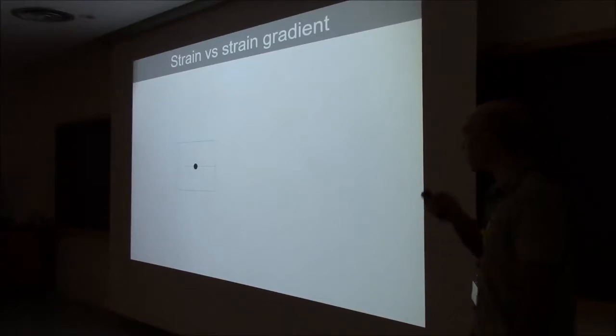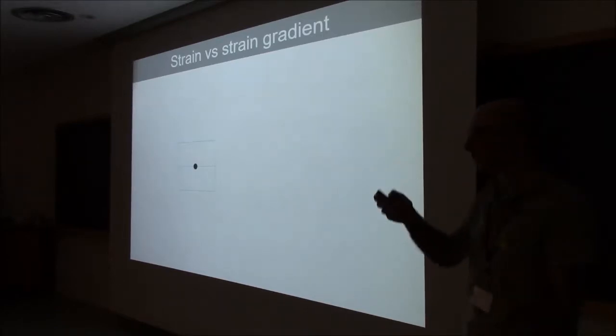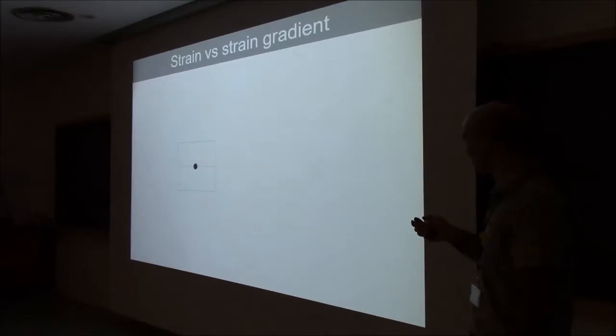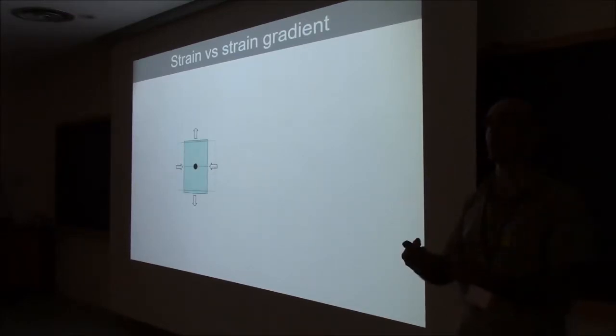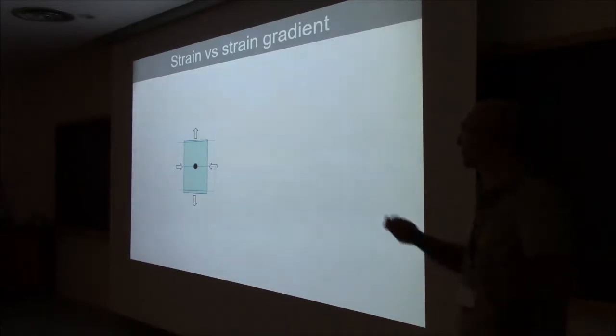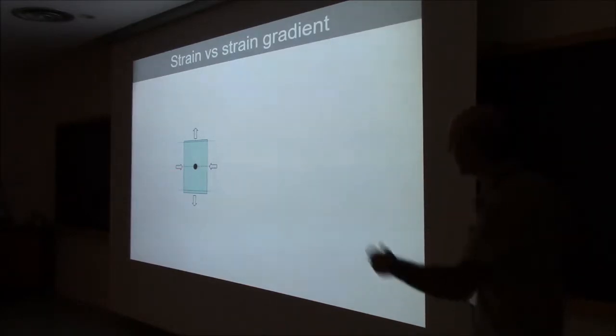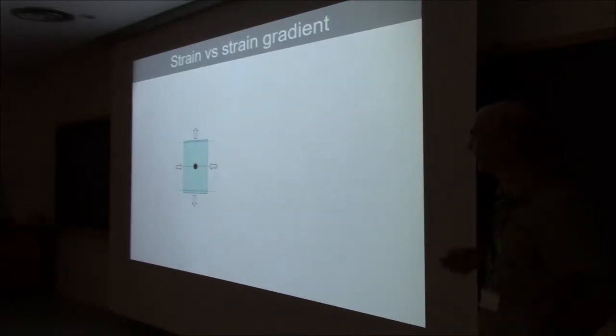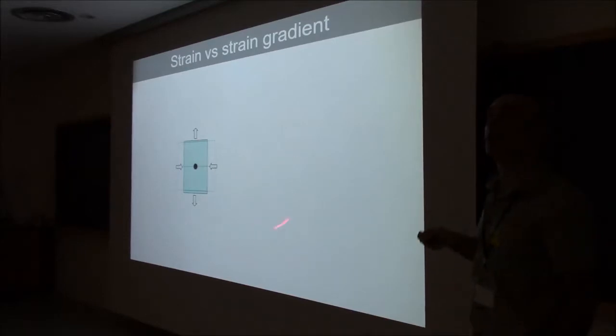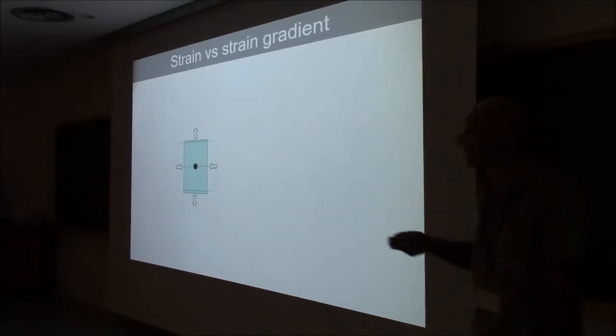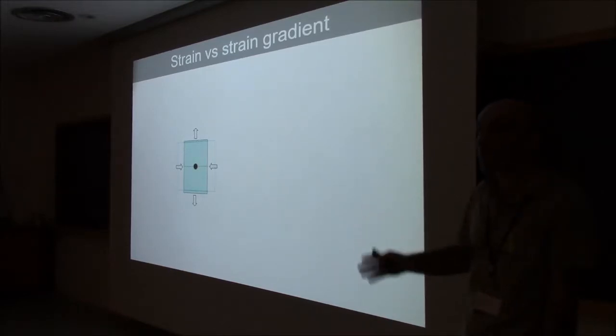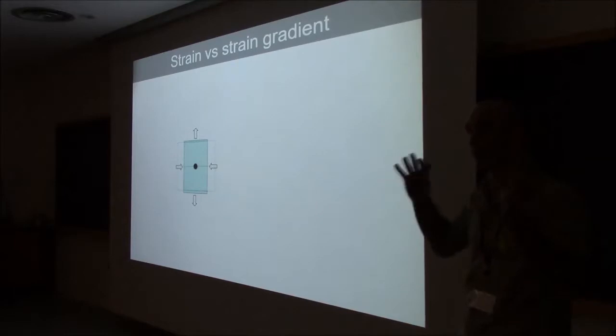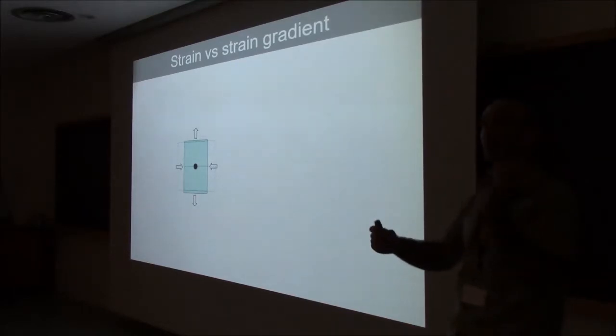Okay, so just to emphasize again this thing because it's quite important, if you start with the centrosymmetric unit cell and you apply a homogeneous deformation, which is by definition a symmetric deformation, so you apply the same force from either side, you either compress from the sides or you extend from the top and the bottom, you will of course change the shape of the unit cell, but you will not break the symmetry. Okay, it was symmetric to start with, the forces that you're applying are also symmetric, therefore the end result must be symmetric. So you have something symmetric and you apply symmetric pair of forces, you will not get polarization.